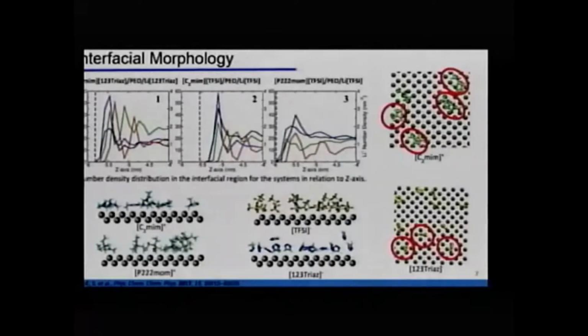Why does this happen? This happens basically because of the size and the shape of the cations. This is imidazolium, so we have a ring, a planar cation, and because of the ring, imidazolium can go very close to the surface and adopt some kind of parallel stacking to the surface, so the interaction of the layer is something like this. But in the phosphonium, phosphonium is bigger and more spherical, so we have a kind of random distribution of the cation close to the surface. That means that we have the broad distribution here.